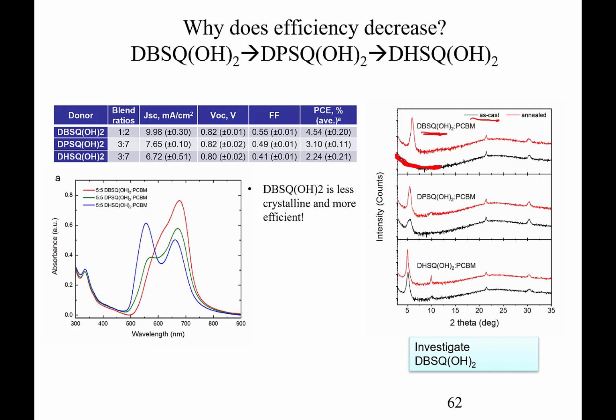When we start to anneal it, then we can bring in this crystallinity as evidenced by this peak in here. On the other hand, with the DH-SQOH2, with the hexyl side group, upon spin casting these devices, we immediately see a crystal structure. And so that's why we see the double hump in this blue curve in here on the left-hand side. So we can investigate, of course, the DBSQOH2. That's where we spend most of our efforts these days in the Collison lab.